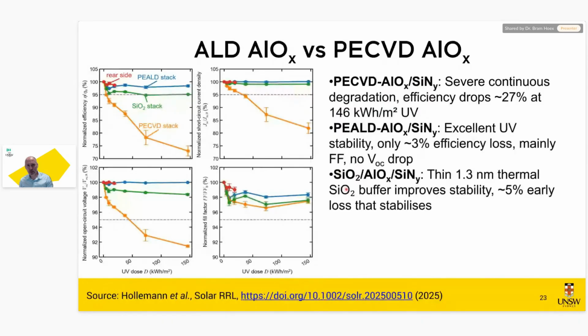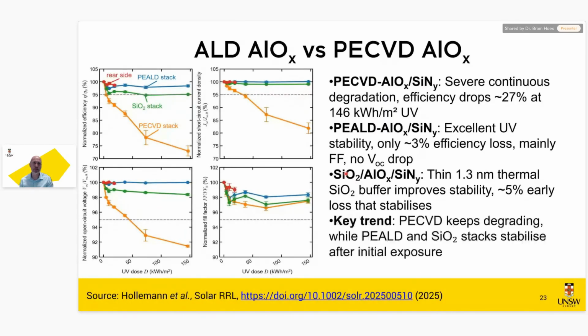But they also show that if you just make sure that your silicon oxide film is of higher quality, in this case they used thermal oxide to make the silicon oxide layer, while in these two cases they rely on the silicon oxide that is formed during the process. That also made the cell a lot more stable. So this clearly points towards making sure that you have a very good interface, so the quality of your interface will determine how sensitive you are.